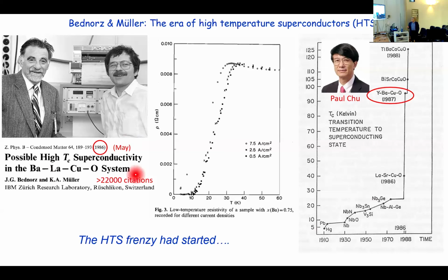And you can see that this is a plot of the original paper. And this is a plot from 1988 from a conference that I went to that year. And you can see they show very spectacularly the slow improvement of TC over 70 years. And this jump of 60 or almost 100 Kelvin in a couple of years.